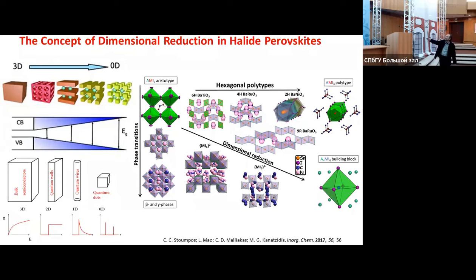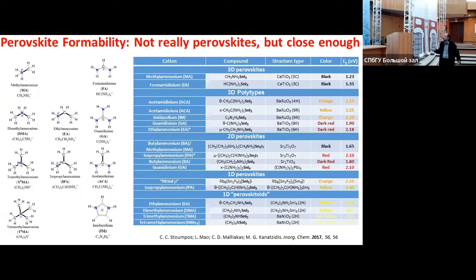And if you start with this lattice, I talked to you about the phase transition, there are possibilities. What will happen if you try intermediate size cations? Is it possible to do chemistry? The answer is yes. And for the case of tin, for example, if you try this selection of small cations that may closely fit or slightly off, you end up with a palette of materials going from the perovskite black phases to yellow phases. Sorry about the color here. And you get a palette. You don't get the same thing.